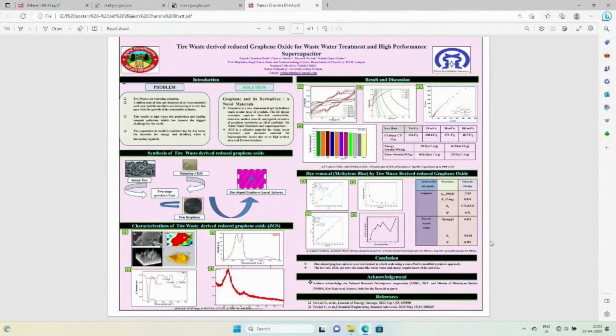Our synthesis part is: we collected the waste tire from the local region of Nainital, cut it into small pieces, and washed and dried it. Then we mixed it with a fixed amount of catalyst, and after primary and secondary pyrolysis, we got the raw graphene. After washing and ball milling, we got our synthesized material, which is confirmed by different characterizations. The SEM images indicate the surface morphology of the synthesized material, and the Raman spectra show the D, G, and 2D bands respectively, which confirms this is RGO. The FTIR data and the XRD data support this statement.